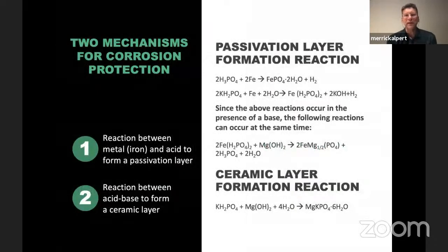So a little more detail on how this works. As you have the bucket of A and the bucket of B, they go through the plural component pump and get sprayed onto the steel. The first thing that happens is that you actually have two mechanisms for corrosion protection. The acid component goes into solution, it touches the steel, and it draws the Fe, the iron, off the surface of the steel. That is what's going to form the passivation layer. That's the most important thing that's taking place when you spray the Eoncoat onto steel.